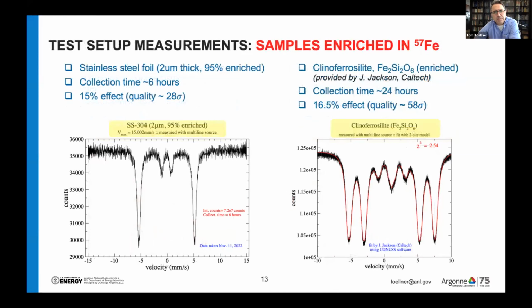So, some test measurements. I measured some enriched samples here. These are stainless steel on the left-hand side. It's the 2-micron enriched stainless steel. This collection time was about 6 hours. Again, with the new spectrometer the data rate will be 60 times faster. So this is the kind of spectrum you would expect from this enriched stainless steel in about 6 minutes of time. I didn't have time to fit the data yet.